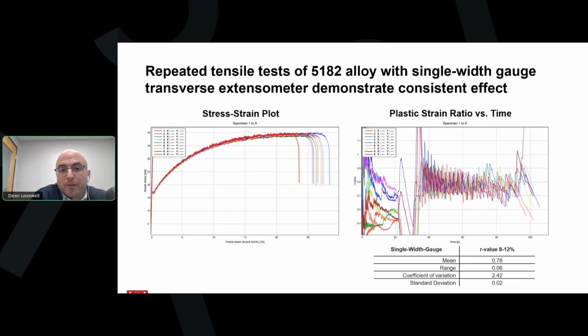In speaking with producers at the time, we were told that in order for them to ensure they met formability requirements, they essentially had to plan for the very bottom of the range of R value in order to avoid producing non-conforming material or material that required multiple retests. Now, in order to do this, they would work to lower composition levels of magnesium, although this would prevent them from missing their R value requirements. It meant that they were sacrificing strength to do that. And still, they were delivering material with lots of variation in the certified value.